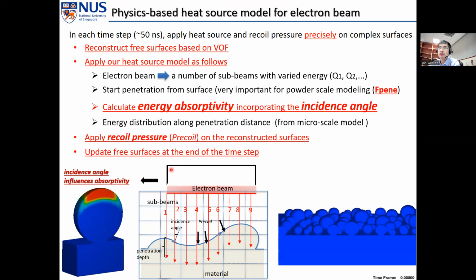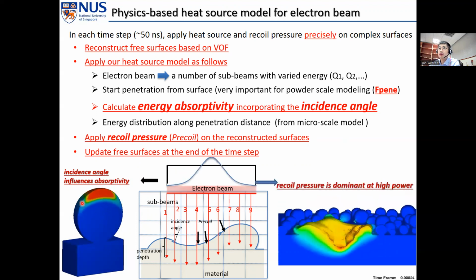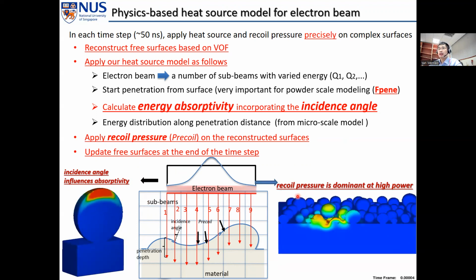We assume it's a uniform distribution in the cross-section of the electron beam, incident on the spherical particle. And you can see the incidence angle is 0 here in the center and becomes larger and larger to the edges. So the energy absorptivity is highest in the center and becomes lower and lower to the edges. So that's the reason why the particle gets melted in the center first and then the edges. And for the commonly seen Gaussian distributed electron beam, if the power is high enough, the recoil pressure will be dominant so that you can see the keyhole formation.